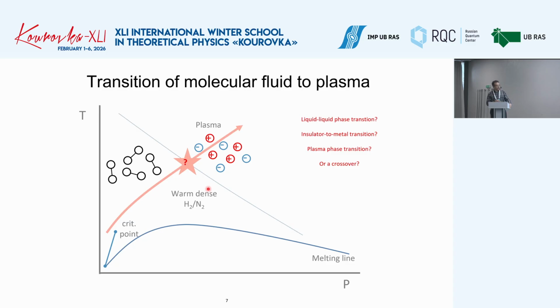So our major point is that we think that the equilibrium thermodynamic picture is not good in order to describe the very fast experiments that people use to study this phase diagram. And our non-equilibrium excitonic picture fits better for this purpose.